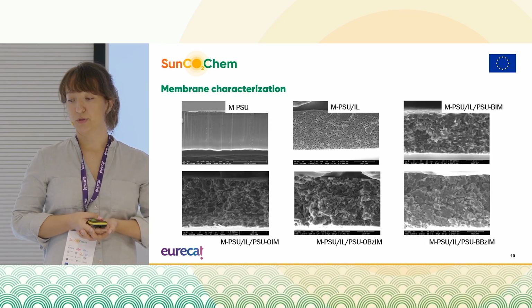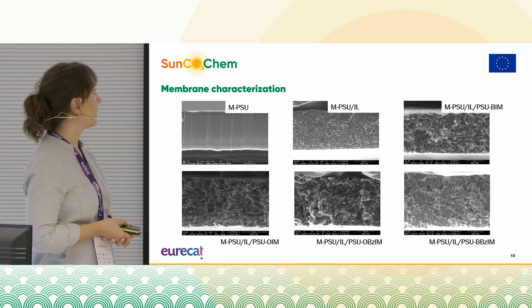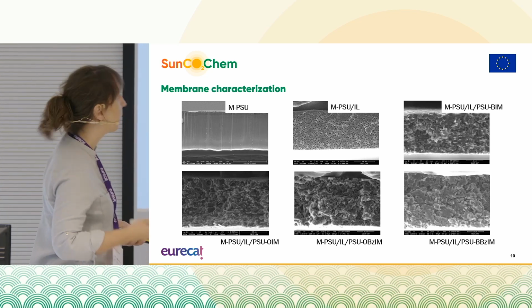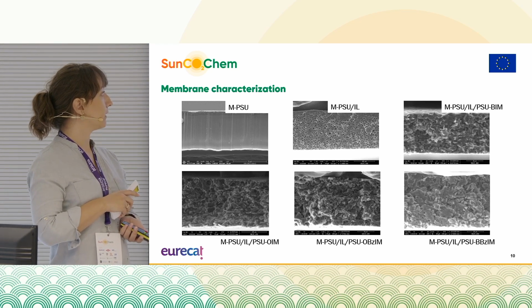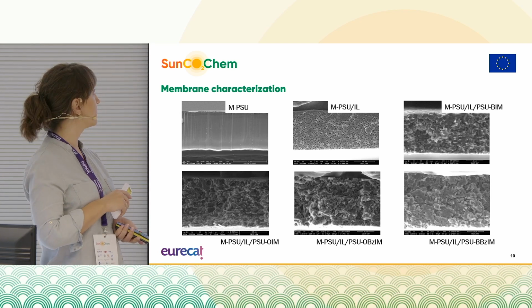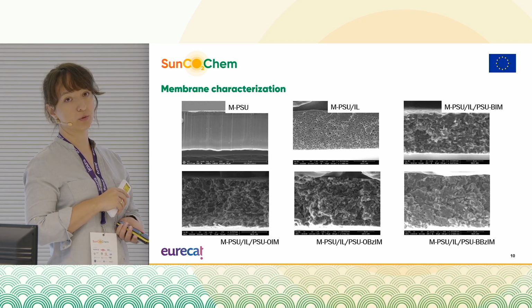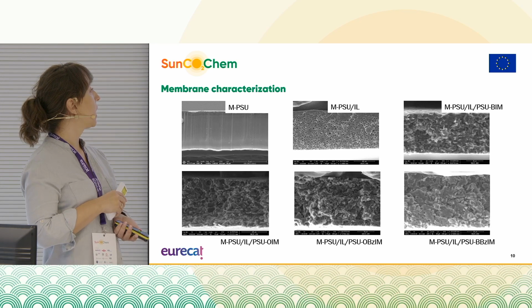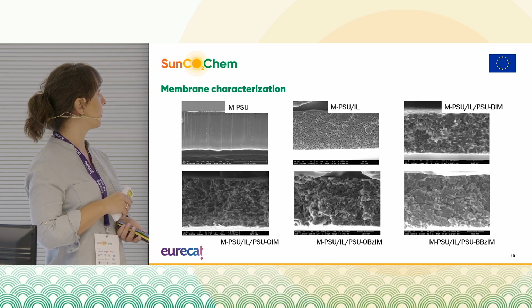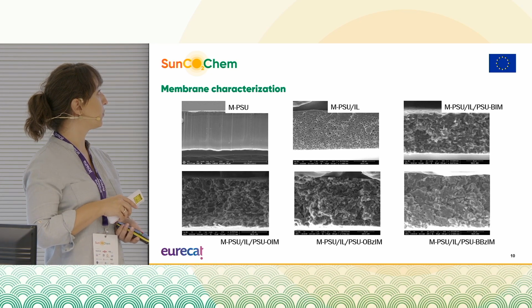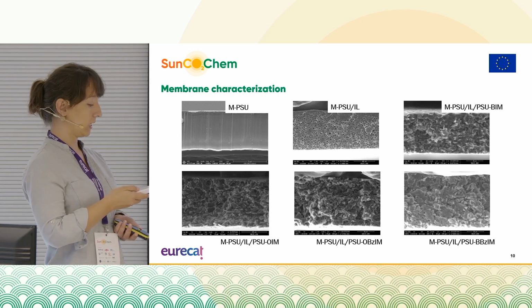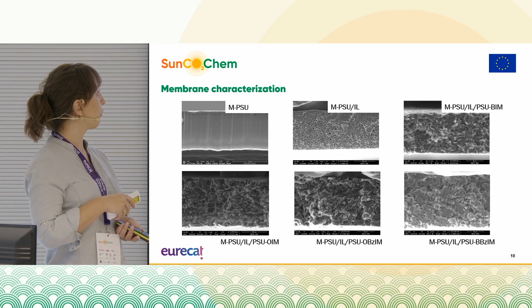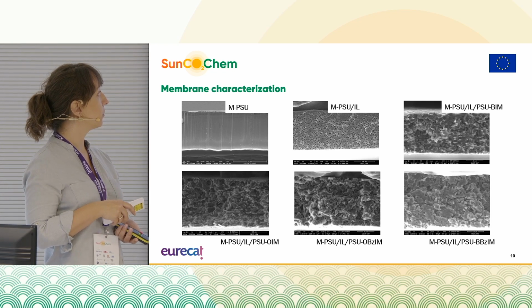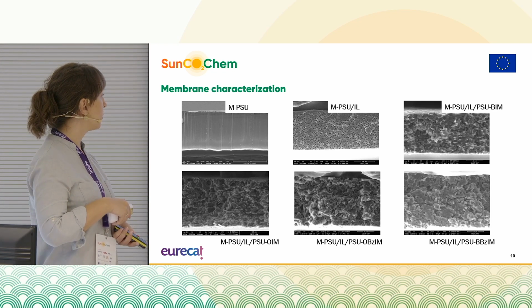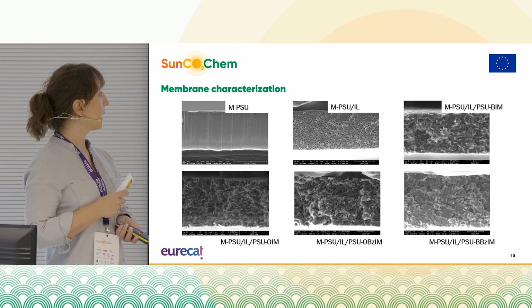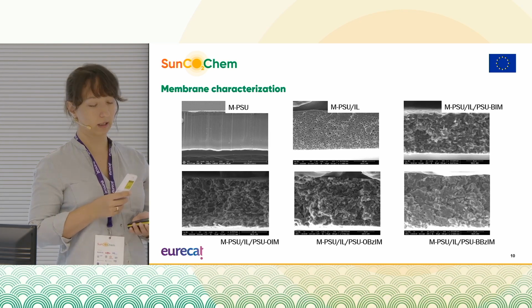Depending on the composition of the polymeric solution, we obtained different internal structures of the membranes. When we used only polysulfone dissolved in the organic solvent, we obtain a dense membrane. Once we introduce the free ionic liquid just physically, it's inducing a formation of pores. Then through further incorporation of the modified polysulfone, we obtain amorphous and asymmetric internal structure.